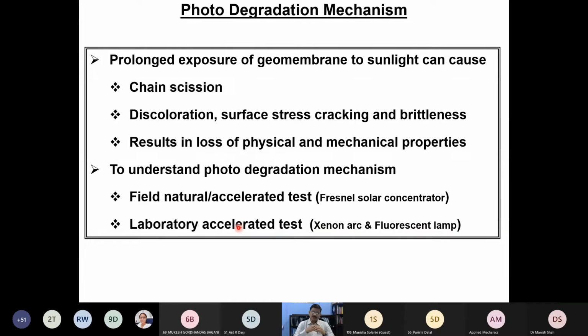This kind of prolonged exposure of a geomembrane to sunlight causes chain scission, because a long molecule, a long chain, is subjected to scission. That means a big molecule becomes small pieces, and sometimes this causes discoloration. You might have seen this, for example, with a plastic chair: if you throw it in a garden for 2 to 3 years, you will see the plastic has changed its color. Not only that, if you scratch the surface of the plastic, you may get it in powder form. That means degradation of the polymer might have taken place completely. Surface cracking and brittleness are also possible results.